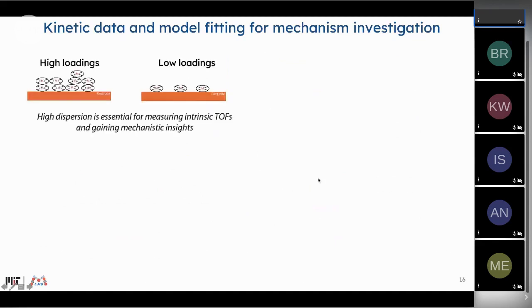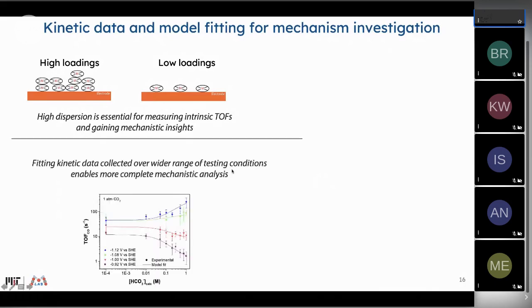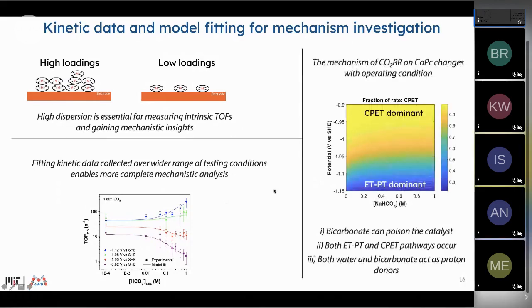So just to wrap up here, what I want to emphasize is that understanding of loading is critical for understanding turnover frequencies, that one needs to really pay attention to whether these systems are aggregated and hence are not reflecting kinetically limited activity. Fitting data over a wide range of testing conditions enables more complete mechanistic analysis. We see that the mechanism appears to shift depending on the regime in which we're operating, and that we can get a very fine understanding of how one can tune the system between being electron transfer, proton transfer dominant, or CPET dominant. And there are ways to also then, perhaps in the future, mitigate bicarbonate poisoning and enable lower overpotential operation with higher turnover frequencies in these sort of systems.